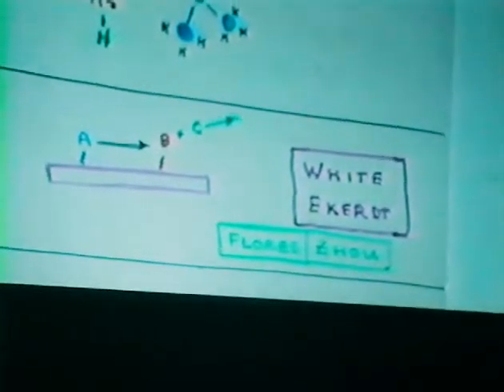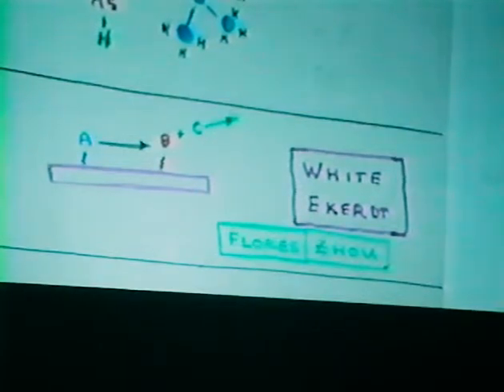What you do is you get an ex-catalysis guy like John Ekerdt interested in this problem. He's somewhere between this little diagram, which represents chemisorption and desorption, which is my area, and thin film growth, which would be the next panel. The point is that we can't do this second experiment unless we've got the first guys in line, and they've got to be willing to stay with us long enough to tinker around with those ligands up there based on what we see leaving as C or being deposited as B.